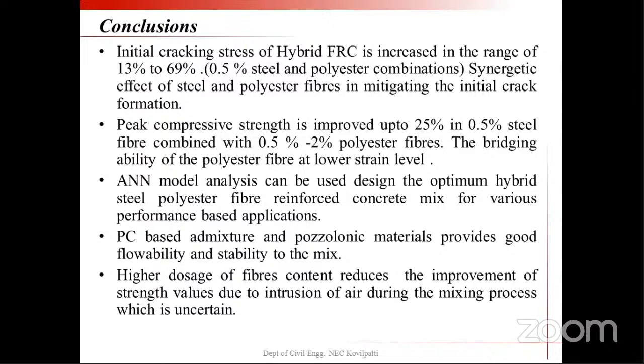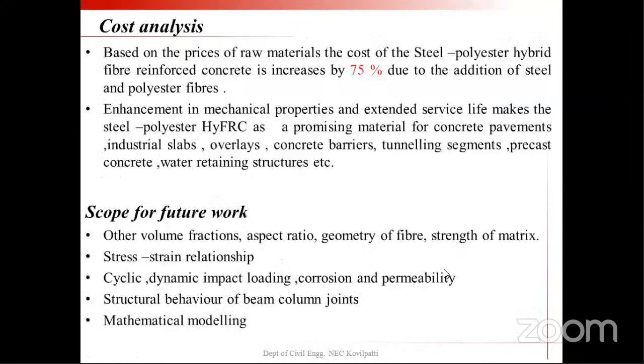So what I did is, after getting the experimental observation, I understood the behavior. I made some ANN modeling at the end of the experimental part, so I have included that point also. And I want to mention the PC based admixture provides effective dispersion of fibers and flowability and stability to the mix. So this PC based admixture is highly recommended, and a higher dosage of fibers reduces the improvement mainly because of the polyester fiber intrusion of air during the mixing process, which is unavoidable. So that causes some decrease in the strength values.